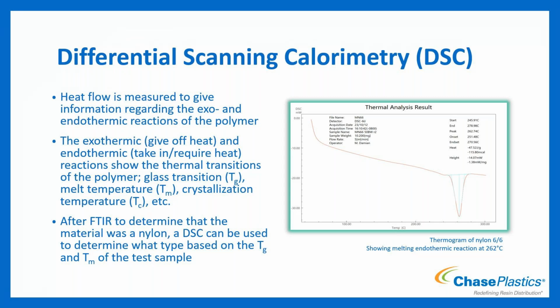And so what you'll see over here in this curve is the endothermic reaction down here. It is taking in the heat to melt. And so this is for a nylon 6,6. You're showing the reaction on this particular one at 262 degrees Celsius. And so we know the TM of nylon 6,6 is right around 260, 265. So that would be right in line with what we would expect it to be and what it is showing us on the curve itself.